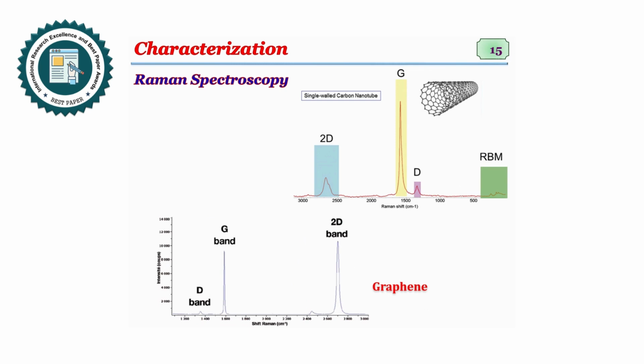Similarly, Raman spectroscopy is another important tool for characterizing graphitization and defects. Highly graphitized carbon nanomaterial can be characterized by Raman spectroscopy. High graphitization leads to a large G band, and defects lead to the D band. The 2D band is the double of the D band, and we can analyze the graphitization and the graphitization ratio from the G and D bands.